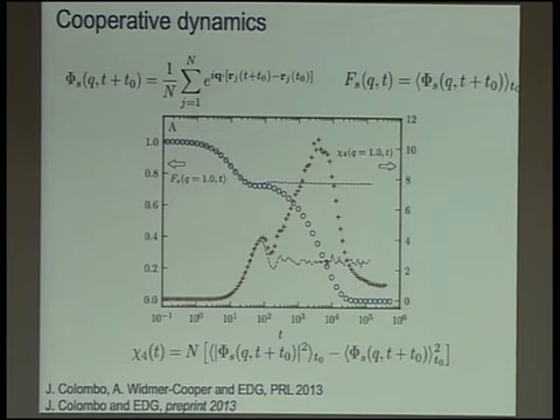Okay, so starting from this, then you can look at the microscopic dynamics of this type of networks, and this already tells you something interesting, I think. So here this is quantified in terms of the intermediate scattering function. That is what you can measure, for example, with light scattering, and that you can compute in the simulations just from the particle coordinates, and it's basically a way to measure the correlation in the particle displacements over a distance of the order 2 pi over q, where q is the wave vector. Okay, so it tells me how the displacement of one particle actually becomes uncorrelated over a distance of 2 pi over q.